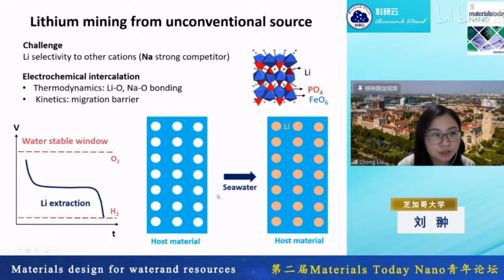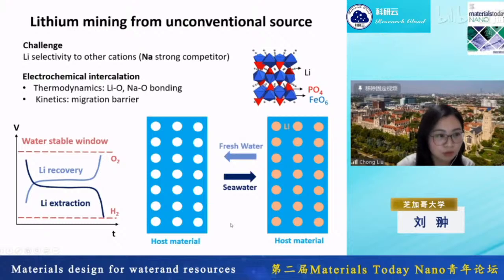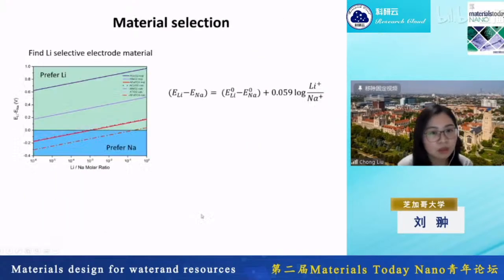You let the material work on the selectivity and hope that you extract all the lithium out of the solution. And then you can recover the material and do a reverse electrochemical reaction to reject the lithium into a fresh solution to recover it. So now the question becomes, what kind of materials are good for lithium extraction? So the first thing we can look at is the lithium to sodium intercalation potential difference.